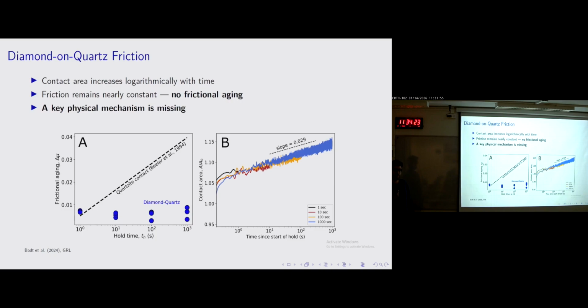This is despite the fact that contact area grows logarithmically with the hold time. This is 4 different holds during the hold. You see I put here a slope of about 0.039. And contact area is normalized by the contact area at the beginning of the hold. You can see it increases logarithmically for 1 to 1,000 second holds. So we're missing a key physical mechanism here.